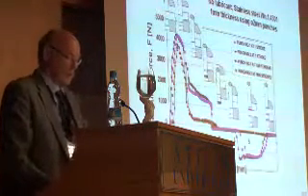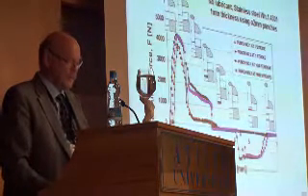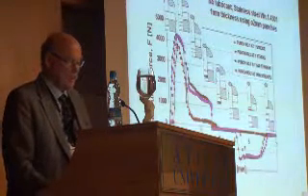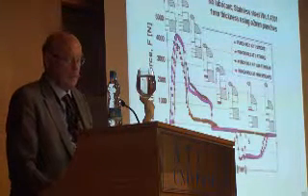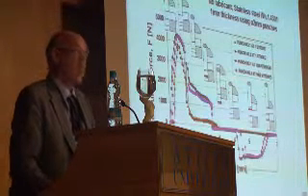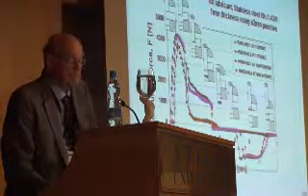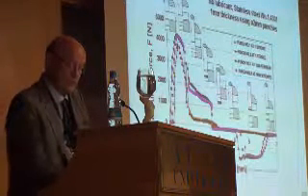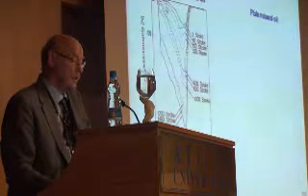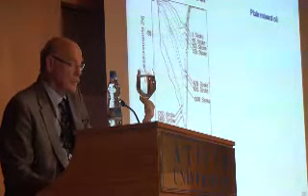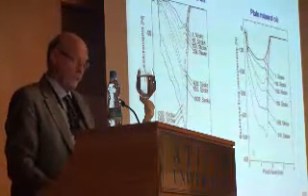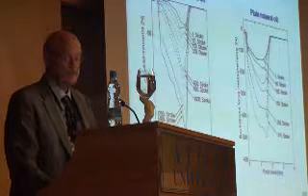Looking at the punch load, for the first stroke, that's the two lowest curves with the triangles, the red and the black for the two punches. It increases and decreases to 0 when you penetrate the plate, and when you withdraw the punches, there is no backstroke force. But at stroke number 1600, you see a vast increase in the backstroke force. This is due to pickup of workpiece material on the punch stem. And this pickup develops quite gradually. You see how gradually from the first stroke the backstroke force increases, here for chlorinated paraffin oil, here for plain mineral oil, and the scale here is 3 times as large, so the backstroke force for plain mineral oil is much heavier.